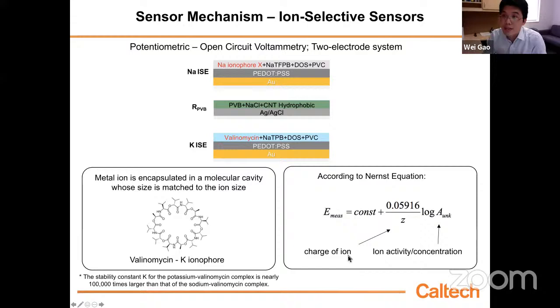If you want to monitor magnesium or calcium, the charge of the ion equals two. In this case, our slope or sensitivity will become roughly 29.6 millivolts per decade of concentration. Of course, for the ion selective electrode, one important factor is the reference electrode. We want to make sure the reference electrode is stable, has a stable voltage over time, no matter how you change the external solution or sweat composition. But if we use a classic solid state silver-silver chloride electrode, by itself, the silver-silver chloride electrode is a chloride selective electrode.